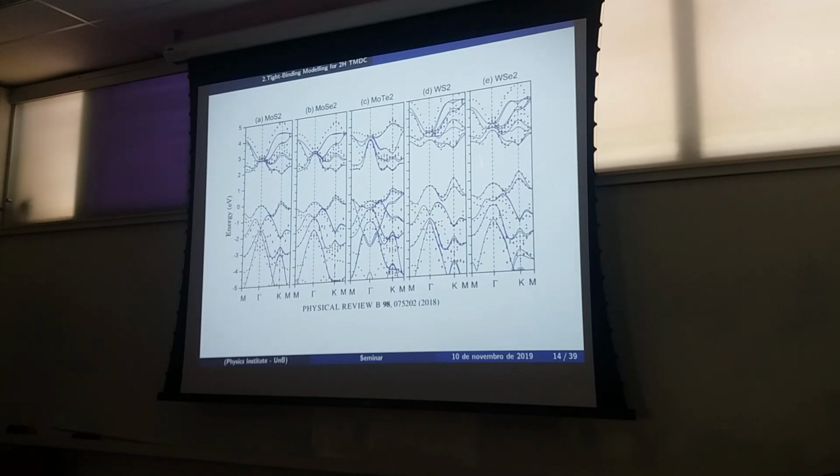So here I'd like to show the fitting that I observed. The red dots are DFT calculations using Espresso with the PBE functional, and the blue curves are my model. I do the fitting with spin orbit coupling. That's important, and few people show this. I try to use spin orbit parameters that reproduce those splittings correctly, and that's important to characterize the material. You see that in the tungsten-based TMDs the spin orbit coupling is higher than